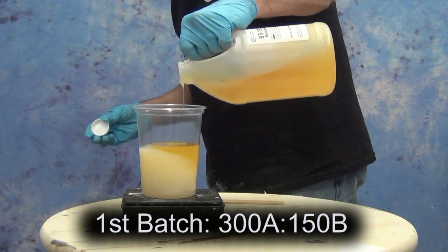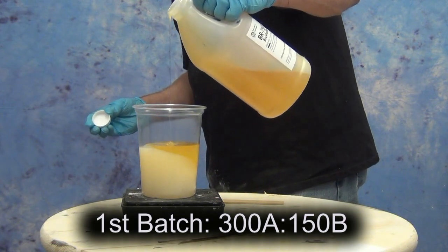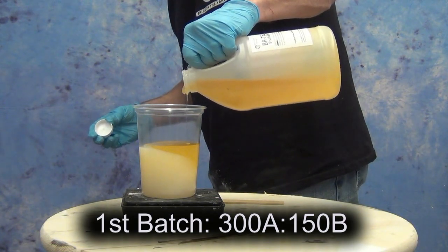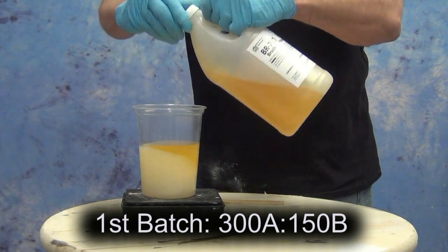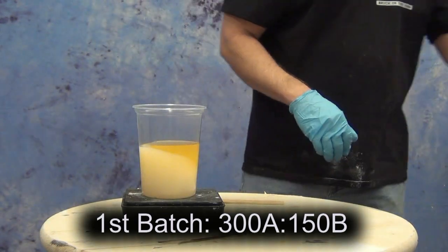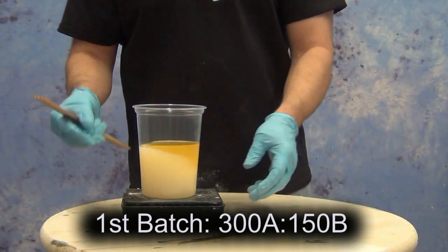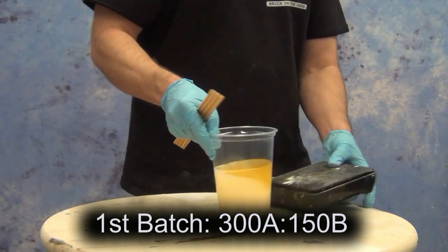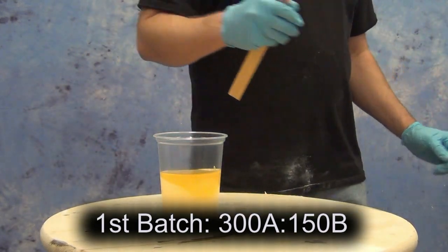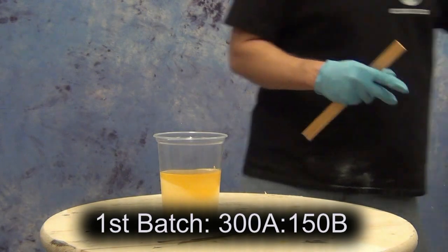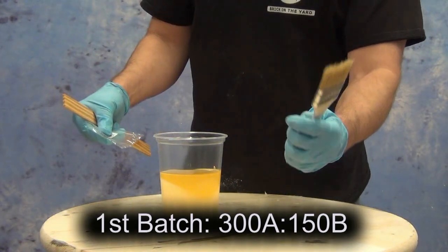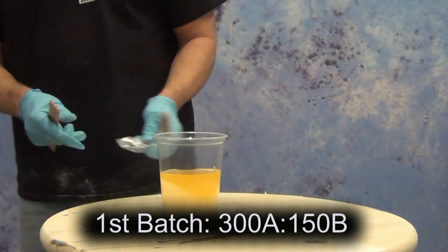Now, when the two components combine, and when they're thoroughly mixed together, they convert from a liquid to a brushable gel, about the consistency of a thick hair gel or like sour cream. So remember that as soon as you put those two components together, you have about 5 to 7 minutes working time, and then about a 2 to 3 hour demold depending on the cross section of the part. Now we're going to apply this with a chip brush.